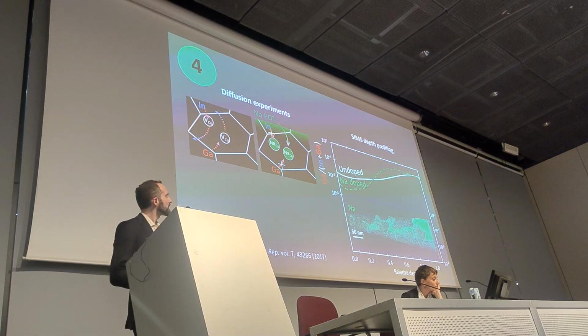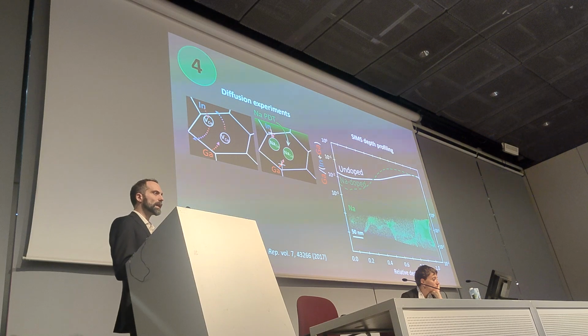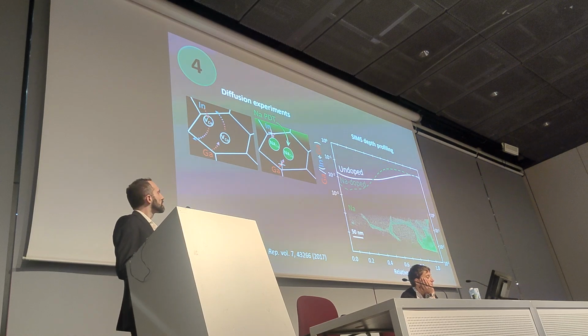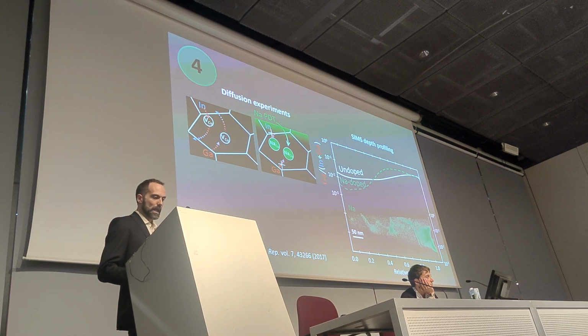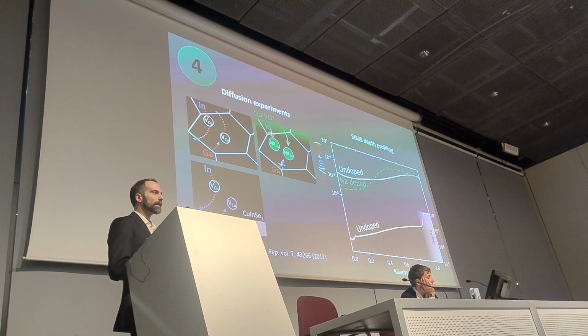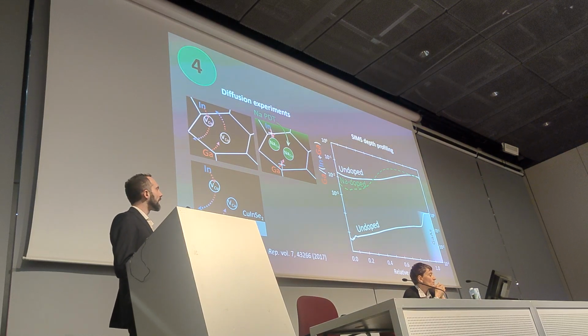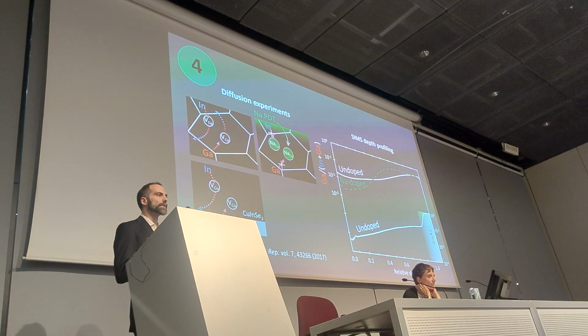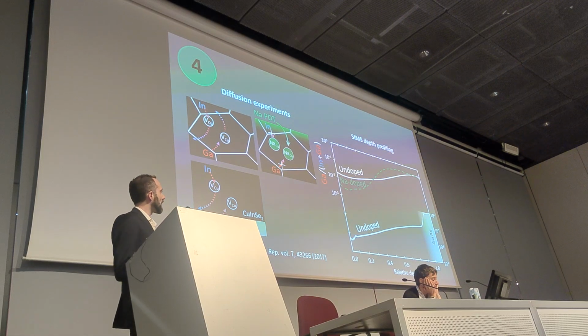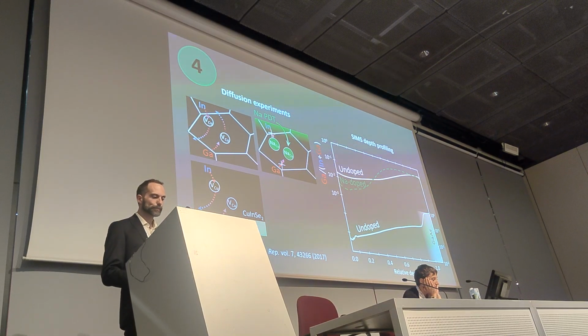But we know the situation is this in terms of sodium distribution within the material. And in the polycrystalline case, we have grain boundaries. So maybe what we're seeing here is a blocking phenomenon caused by sodium at the grain boundaries. So in order to unravel this mystery, we decided to perform an alternative diffusion experiment. We performed a diffusion couple experiment starting from a grain boundary-free configuration. So we grew a copper-indium diselenide epitaxial film on top of a gallium arsenide wafer and observed what happens in terms of distribution of gallium.